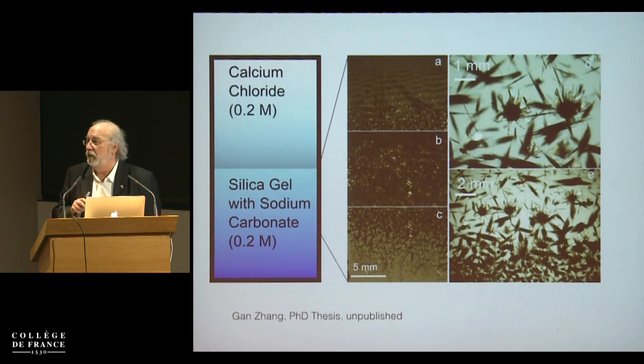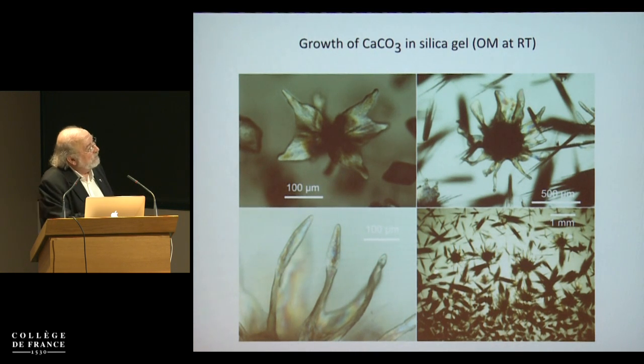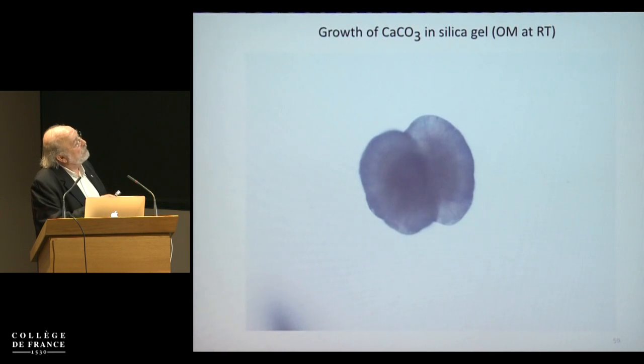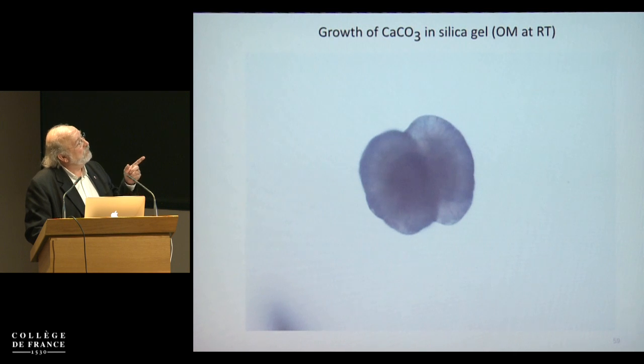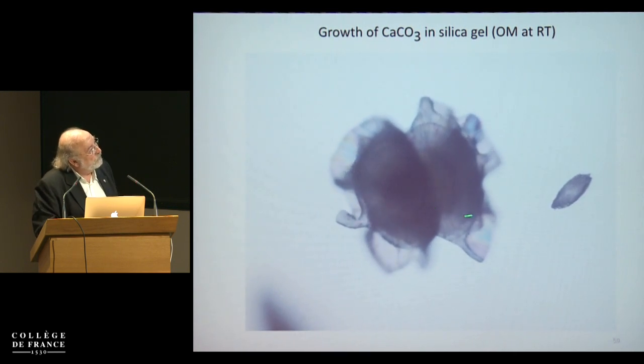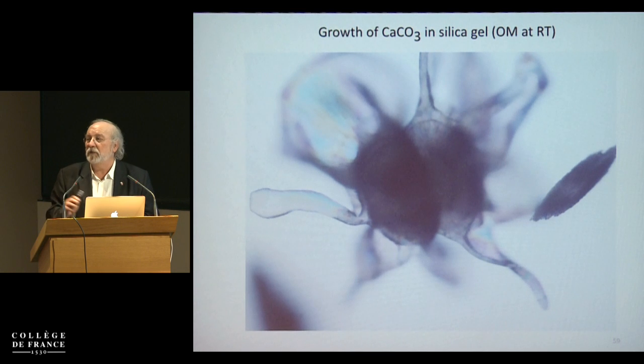This is what I asked you before this morning about, how to explain this. This is the aragonite calcium carbonate. You can see the morphology, which is similar to the biomorph, while the calcite is fibrous calcite. This is a wonderful video, I think, because first of all it explains very well the morphogenetic behavior of the two different phases of calcium carbonate. You have this aragonite growing as biomorph, and this calcite, just 400 microns away from each other, just fibrous calcite, while in the case of aragonite you have this wonderful behavior.